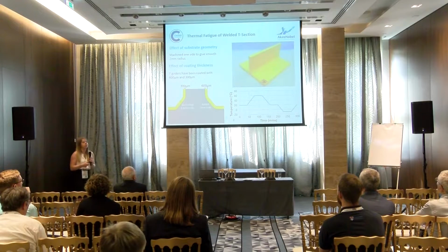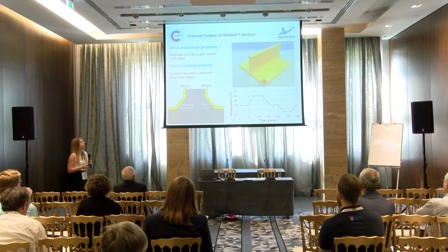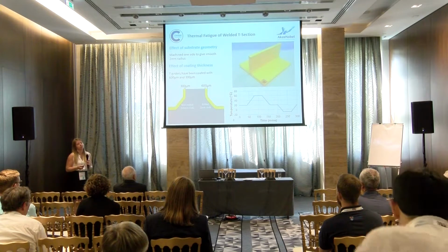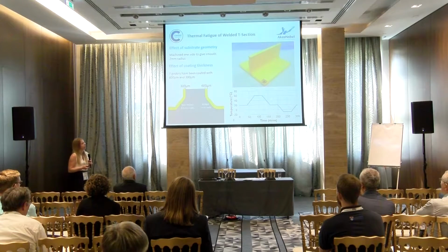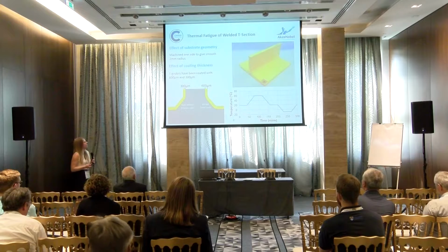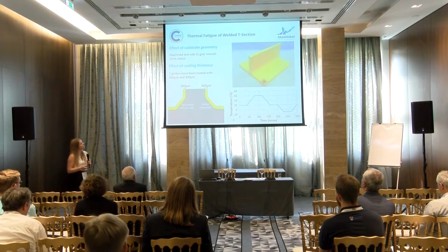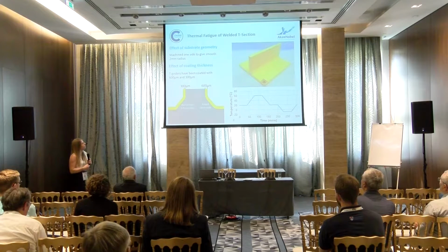And then also, as we saw earlier, the water ballast tanks are embedded very deep within the ship's hull. So this makes application far from ideal for the workers. Even under laboratory conditions, the dry film thickness of the coating can be up to 60% larger than the intended thickness. Therefore, two thickness sizes were chosen, 600 microns and 300 microns.